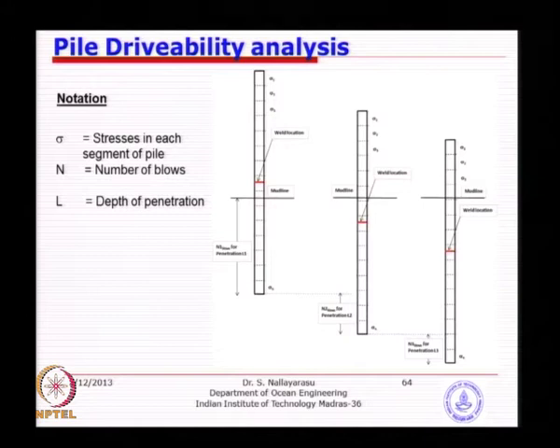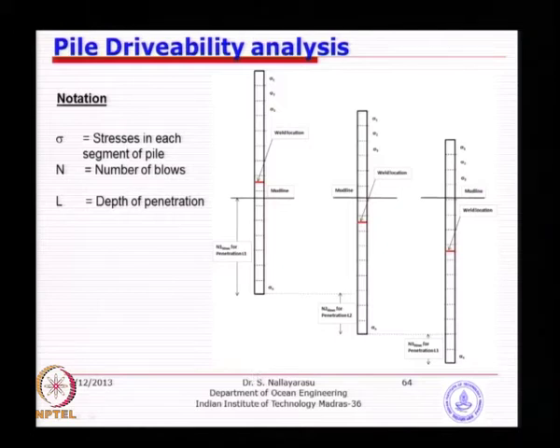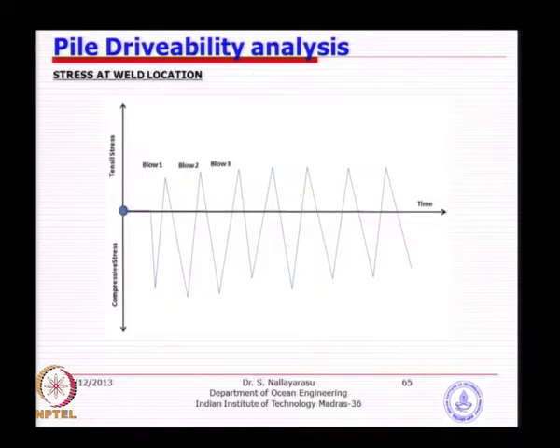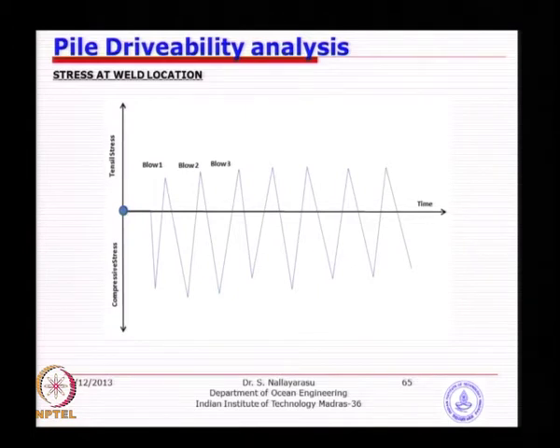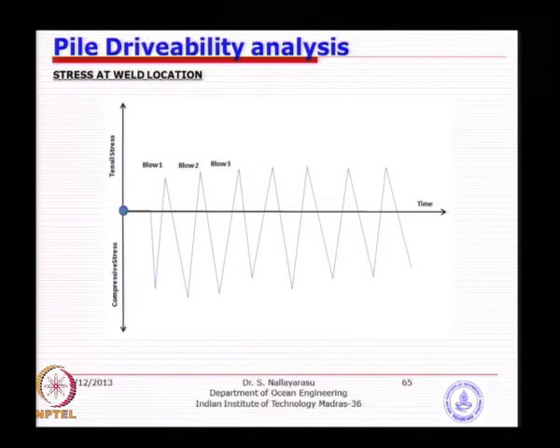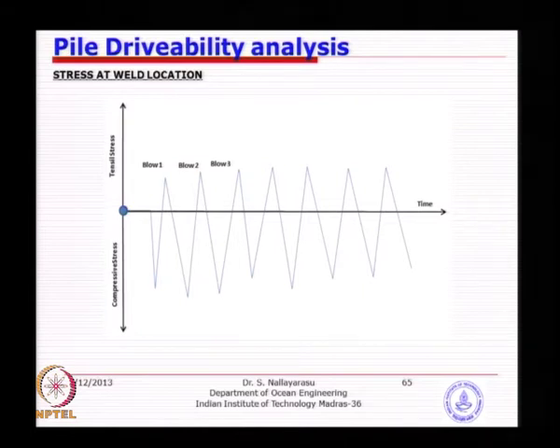What we are interested in is the stresses at the level where there is an interconnection between two segments. Elsewhere, the stress concentration will be lower because it is a continuous thickness. The place where there is a change in thickness or connection is the point of interest. During each blow, the stresses are compressive in nature, travel downwards and then get reflected. Each of these is one cycle, very similar to our wave cycle.